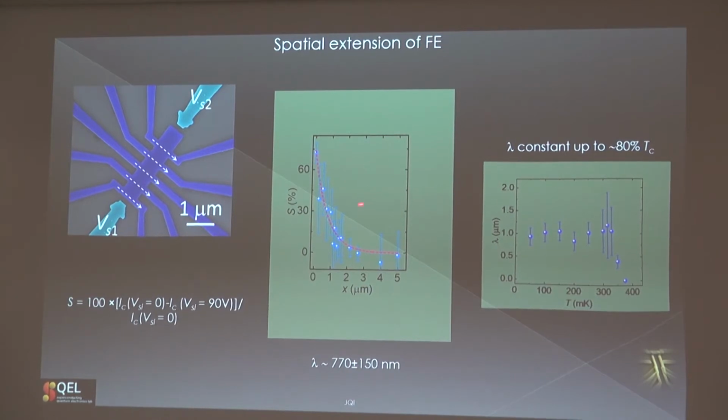Okay, so it seems that spatially it is damped on a scale that is a few coherence lengths. So in some sense, it is giving credit to the fact that we need a mesoscopic superconductor to see the effect, not a large superconductor. So this is why maybe the London brothers didn't succeed, because they were using centimeter-scale samples, something like this cylinder.